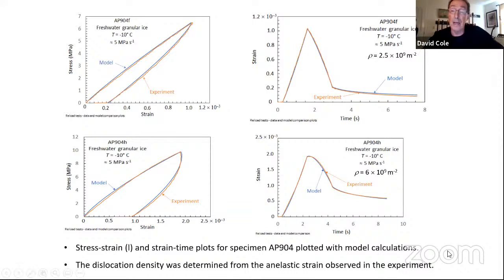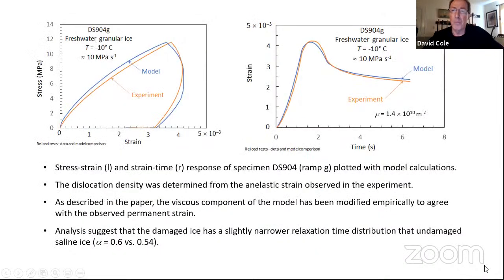So I've primarily, at the highest stress level here, just put in empirically a viscous component to match what we get in the experiments. The main thing, though, we're interested in is the anelastic component, because that's where the strain energy is. It gets dumped back out of the sample. The fit starts getting a bit shakier just before failure, but it's still reasonably credible, and I think we can go ahead and start improving this as time goes on. But I'm encouraged.